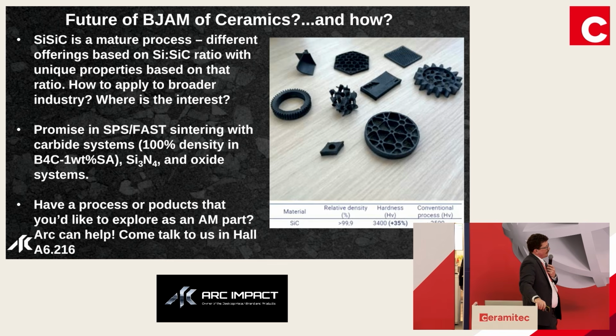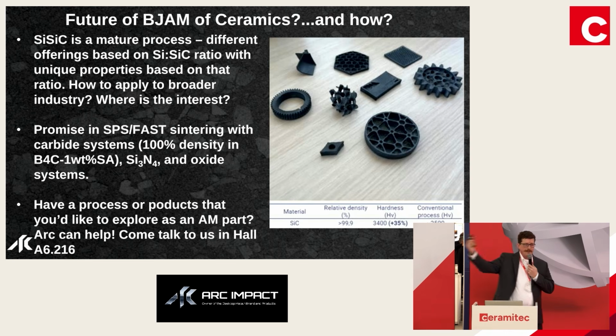As I mentioned, SPS or field-assisted sintering has proven pretty effective in the last couple of years. I've got some images over here of pure silicon carbide that has been densified to greater than 99.9%. You can see there's a little bit of distortion still. Nothing you can't work out with proper optimization and design. We've had a similar effect in boron carbide systems with a small weight percent of sintering aid. We're able to get 100% dense on similarly complex shapes. That's currently limited by size. As furnace developers increase their capabilities and their designs, we can get larger and larger parts out of the SPS process. We've seen similar promise out of nitride systems, and with the proper support media, you can probably see some good advancements in oxide systems.